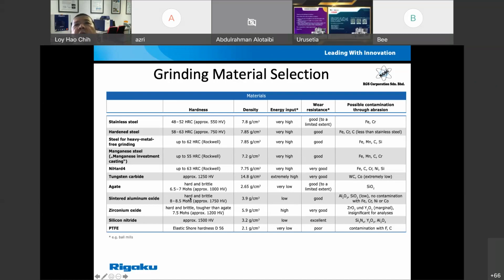Normally, in XRF, beside the hardness, there is also possible contamination through abrasion. These are two things that you need to consider during your selection of your grinding process. In normal applications, we normally suggest customers use tungsten carbide, because the hardness of tungsten carbide is very high, and it will give you contamination of tungsten, carbon, and also cobalt. But this is extremely low because the material itself is very hard.